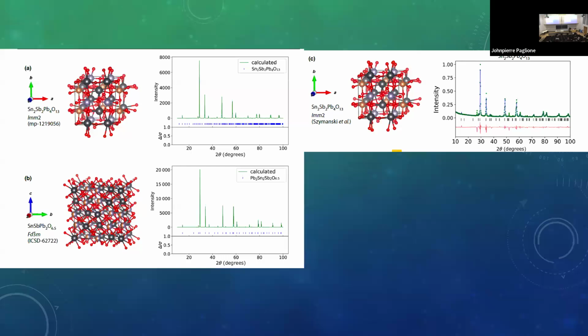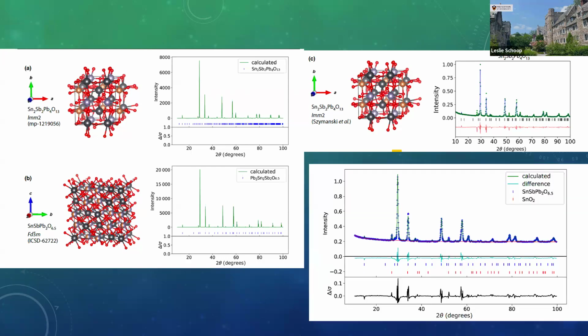Here's their data and their fit. You see the fit is poor. There's virtually no way of differentiating between the two materials. And here's our fit. So we cropped the data. We didn't get the original data, but we used a program to get the data from the images. And then we did our fit with adding the known materials and some impurity phases, and we actually get quite a decent fit, with a little bit better statistics than their fit with the known materials. So there's no reason to assume that this isn't a known compound out there.